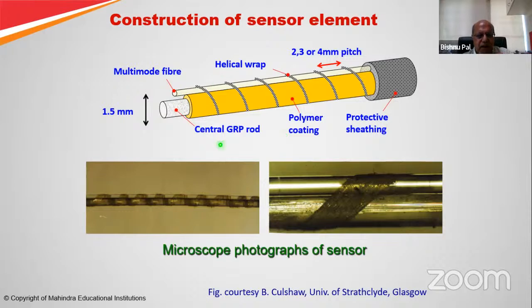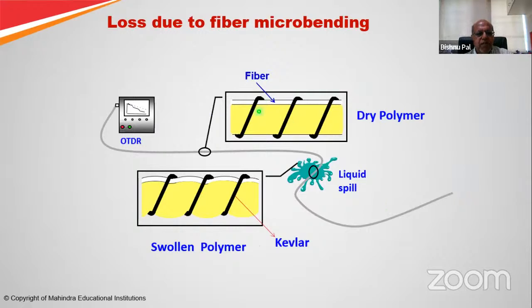Since this fiber is tied with this overall structure, if water anywhere comes in contact with this polymer coating, the hydrogel, that portion will get bigger. As a result, it will start pressing the fiber and create a microbend in the fiber, and you know that microbends introduce losses. This work was done mostly with Strathclyde University people. So it is a dry polymer fiber, stretched and wrapped around the hydrogel. When the hydrogel comes in contact with water, it will swell, creating a microbend on the fiber link. And that leads to loss.